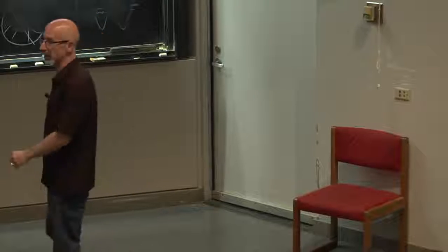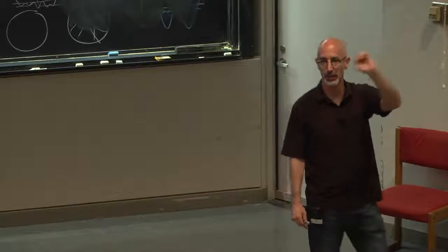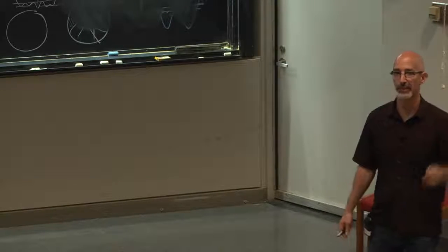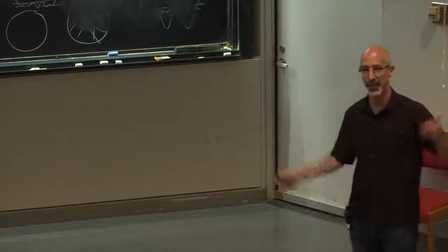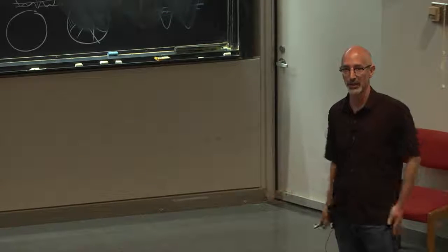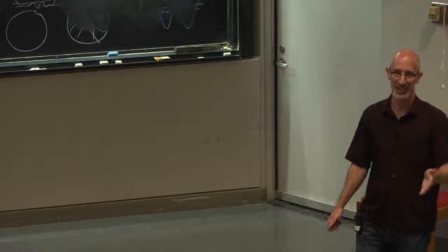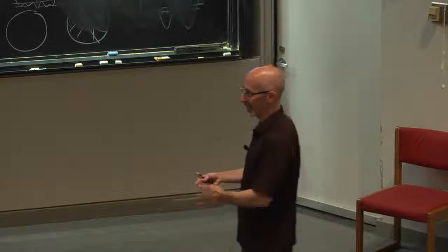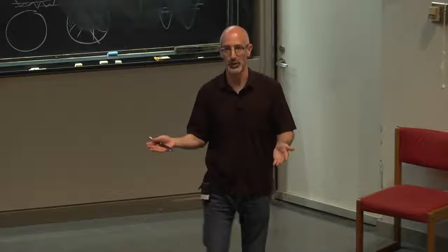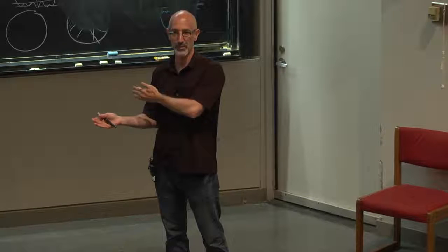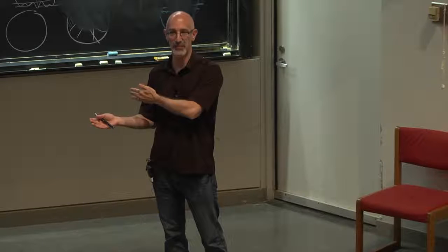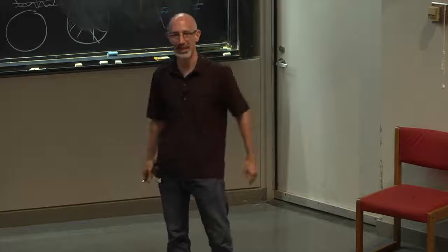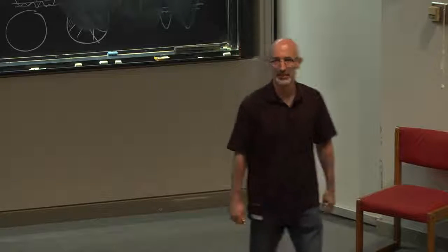To do this really well, you want to basically take the lowest two k points, subtract them and get the length from that, and for that you need a large box. It seems weird that you would need a very large system to extrapolate to a length scale of 5 particles, but this is the way it is.